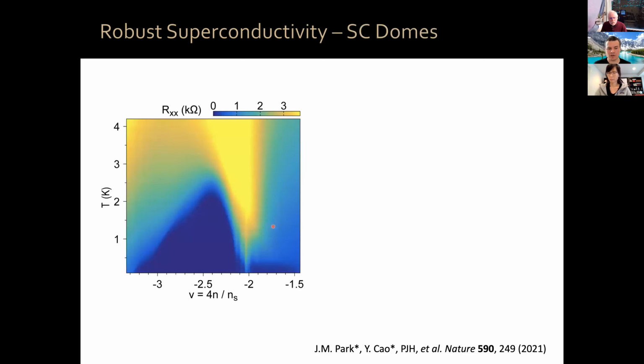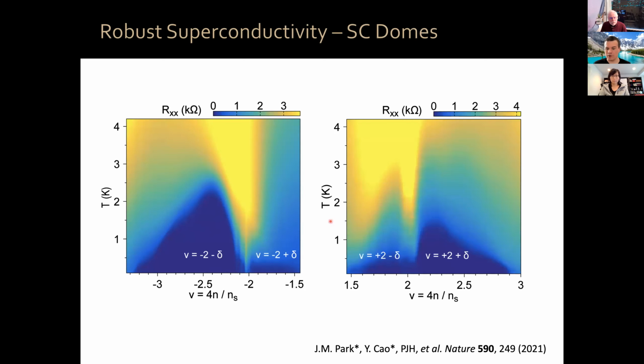We can measure the resistivity as a function of temperature and filling factor. Similarly, the charge density here is normalized by multiplying by 4 and dividing by the superlattice density. So this filling factor tells you how many electrons or holes you have per Moiré unit cell. So we have here a large, around 2 holes per Moiré unit cell. We have a large superconducting dome if we add extra holes. We have a smaller superconducting dome if we add electrons. If we look around 2 electrons per Moiré unit cell, we have similarly a larger superconducting dome for the extra electrons, and a smaller dome when we dope with holes with respect to this electronic system.